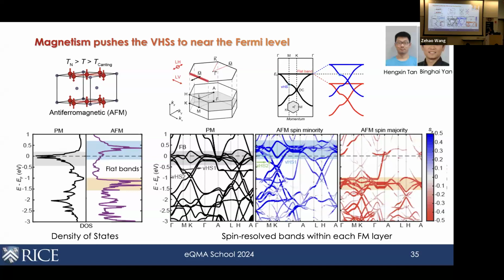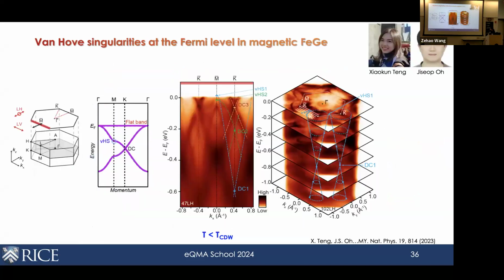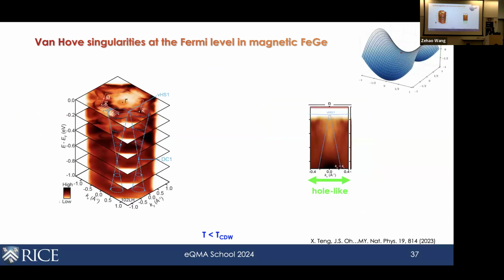So at least theoretically, this is a picture that is reminiscent of what happens in the vanadium-based 135. So experimentally, what do we see? This is a project together with Xiaokun Teng and also Jiseop Oh, who is our postdoc, joined with Bob Birgeneau's group at Berkeley. And they've done ARPES on this material. Just to make a long story short, they indeed observe the Van Hove singularities here very close to the Fermi level. This is a three-dimensional view of the electronic structure of energy versus momentum. You can see this is a direct crossing at the K point, and these bands rise up to the Fermi level into what looks like a Van Hove band. How do we know it's a Van Hove band? If you zoom in, we've got to prove that it looks like a Pringle.